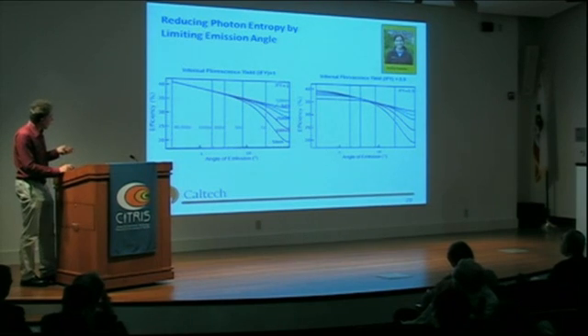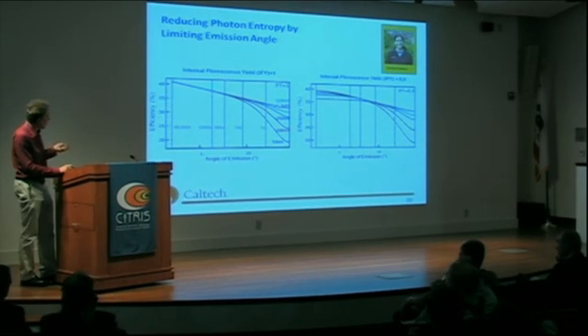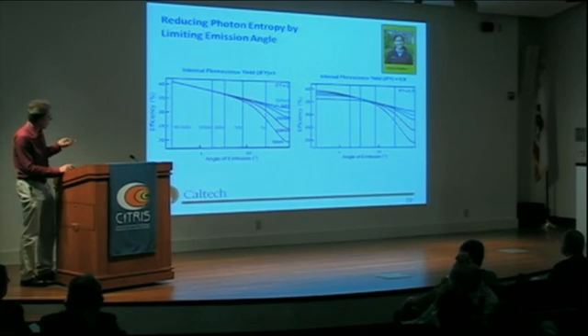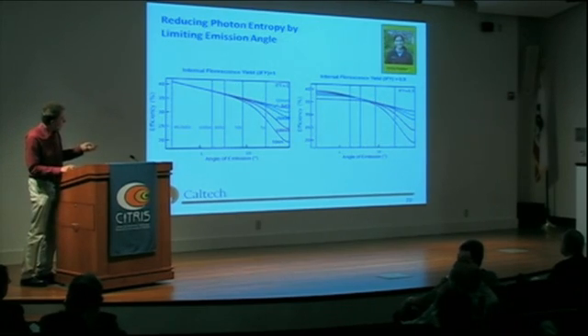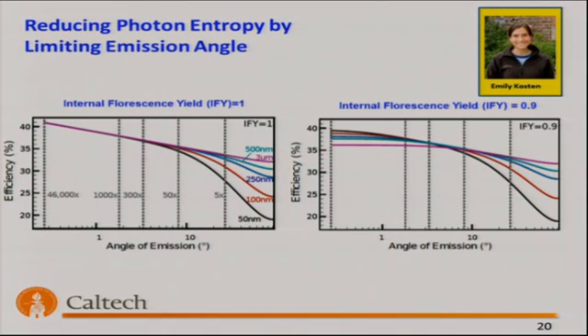So one can also think about attacking the problem of the angular emission by providing collimating structures. If we could restrict the angle of emission, a thin solar cell that has a Shockley-Queisser detailed balance efficiency in gallium arsenide of about 33% without angular restriction could go over 40% for perfect fluorescence yield. Even if gallium arsenide is not perfect, at 90%, which is achievable in gallium arsenide, you can still get very close to 40% efficiency when you restrict the angle of emission down to a few degrees.